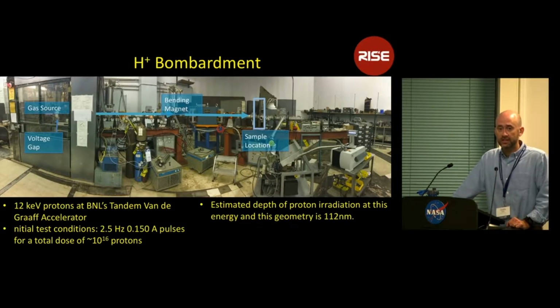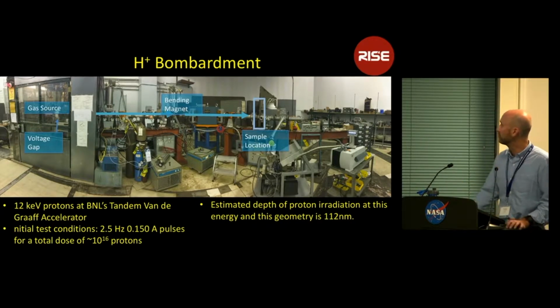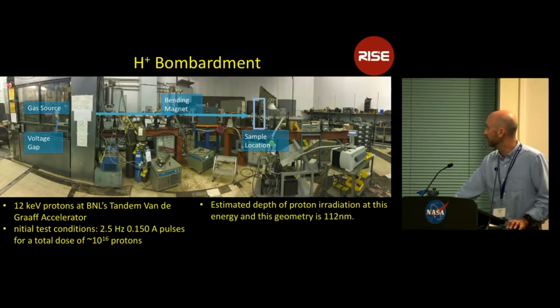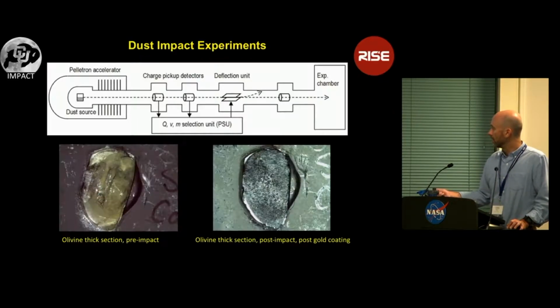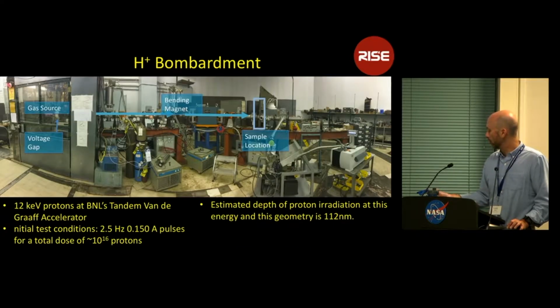Okay, so our first step, I'm going to talk about 2 sets of samples. Some of them were bombarded by protons, others were dust impacted using, well, I'll get to that in a second, and some underwent both processes. We did our hydrogen bombardment experiments at Brookhaven National Laboratory's tandem Van de Graaff generator. Our protons coming out are a little bit higher than solar wind energies. They're 12 keV, but this is about as low as we can get at Brookhaven. And we're using the source because it's right down the road from us and it's pretty convenient.